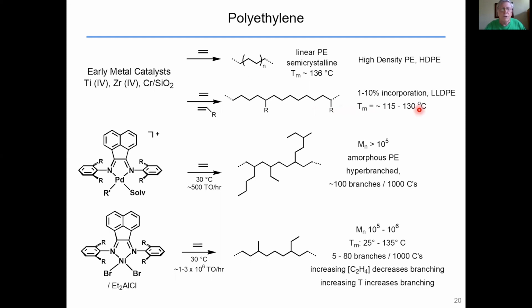and the percent crystallinity. What we see with the palladium systems is that when we polymerize ethylene, we can get high molecular weight material, and it's hyper-branched. You see highly branched materials. They're branches on branches. It's completely amorphous. They're anywhere between 100 and 110 or 120 branches per 1,000 carbons, depending on exactly which substituents you choose.